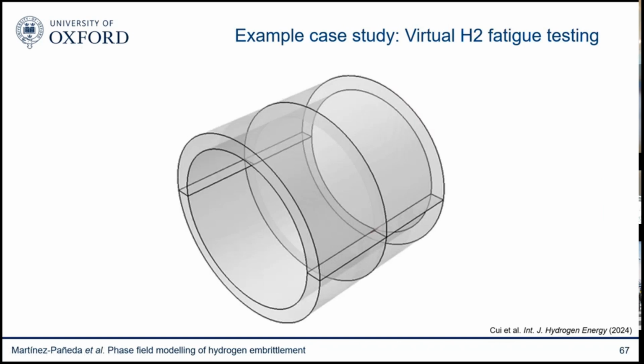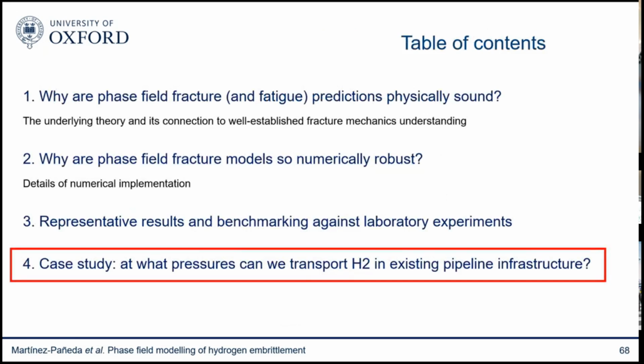And now, of course, because these models can be used not only to reproduce fatigue growth in lab samples, we're also using these models to predict the evolution of the failure of pressure vessels. And we seem to be getting a good agreement with real scale pressure vessel testing. Okay, that takes me to the very last part of my talk, and I think that I'm doing well on